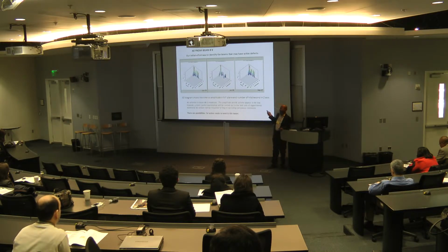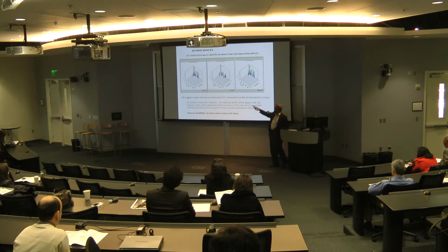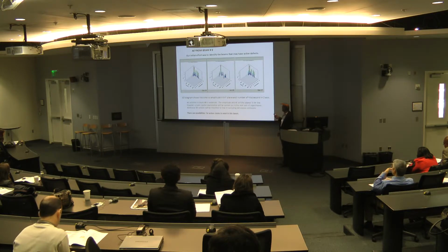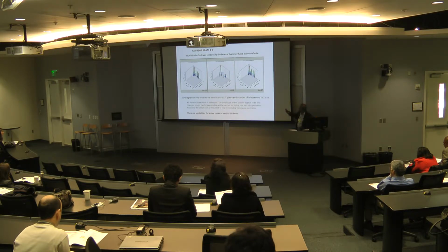That was the kind of test we carried out a few months back, last June, July, September. This is on girder number 8. In June we got some results, and if you see, there's a very small increase in the activity. But it was not clear whether it is going to show any of the defects. We have not gone through full impact. There is a very small indication of increase in activity with time. And we were looking at amplitude and number of hits.